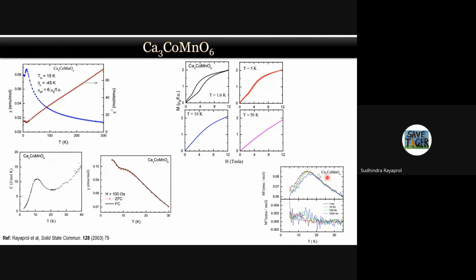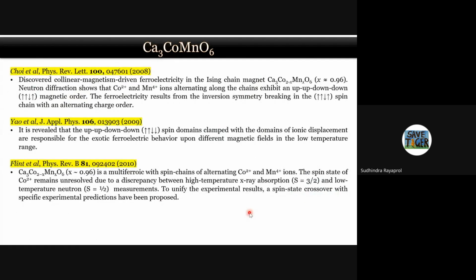And if you look at the AC susceptibility, which rules out spin glassness, it shows there's a magnetic ordering which persists below 13 Kelvin, which is in sync with our Néel temperatures. Okay. So now there were several papers which talk about the presence of spin up-down type of order, which will give rise to ferroelectricity in this kind of system. Okay. Which tells that the system can be ferroelectric.